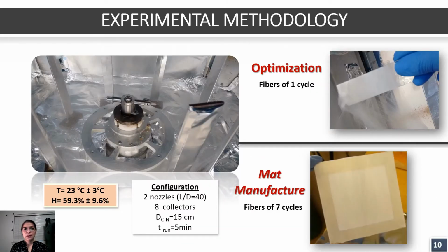And second, the fiber production was carried out in a cyclone machine based on force spinning technology, which is spun with two nozzles, a collector nozzle distance of 15 centimeters, and a runtime of 5 minutes, in an environment at room temperature and relative humidity around 60%. In addition, a glass slide was used for the material collection, as shown in the upper right image.